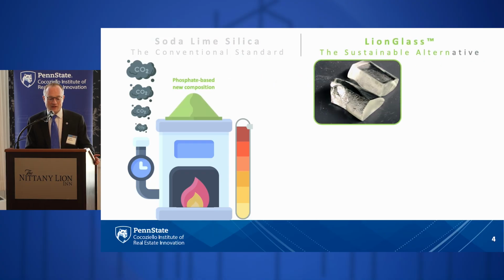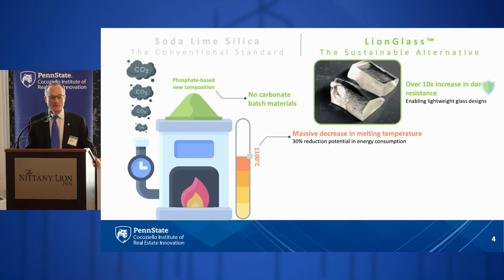What we did with LionGlass is to invent a new family of glass chemistry that completely changes the chemistry of the glass to lower the melting temperature by about 400 degrees C, while also completely eliminating the use of carbonate batch materials. So the melting temperature is brought down to 1100 or even a little bit below that.